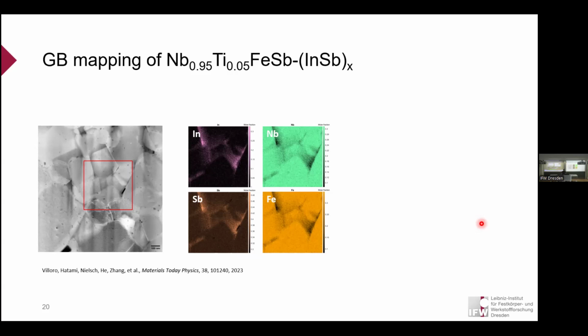But these are not metals. It's a semiconductor, with semiconductor grains, right? The mean-free path is very small, usually less than the grain boundary, I think. The scattering length is in any case smaller than everything, but this introduces the whole notion of a grain boundary. So in the grain boundary you will have several scattering events. So therefore, it's not the grain boundary, the grain has a lot of scattering there. That's my starting point. We simply have a hetero material now.